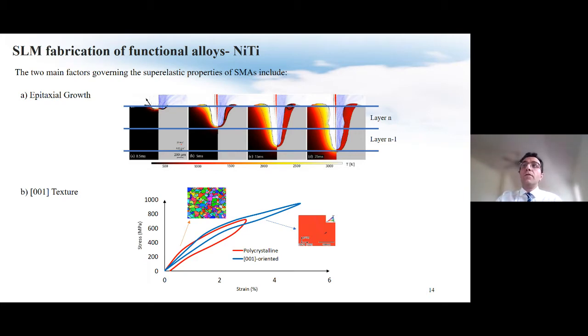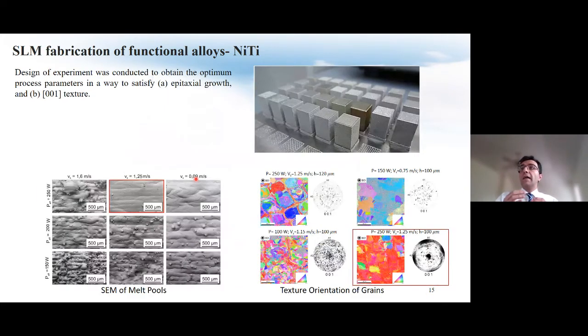Therefore, we performed design of experiment and tried to achieve a set of parameters that result in epitaxial growth as well as 001 texture. After SEM and EBSD analysis of all specimens, we were able to obtain a set of parameters that result in epitaxial growth and produce single crystal. The hypothesis here was that such microstructure, as you can see here, as well as the texture, result in perfect superelasticity. Therefore, the next step was to test this hypothesis.